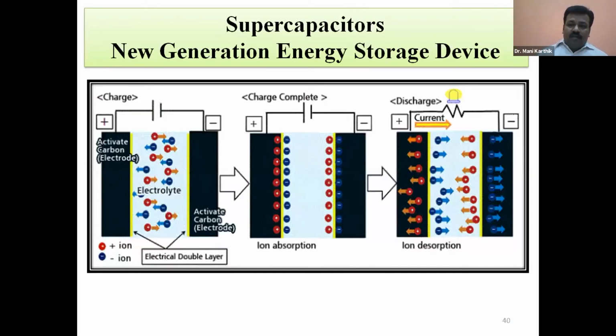So this is the fundamental phenomenon of electrical double layer formation, because porous carbon is coated on the current collectors. If you apply a potential, then because of the polarization, the ions are separated into two different polarities. So we have the formation of the electrical double layer. This is the Helmholtz electrical double layer. Because of this, the charge is stored electrostatically in the activated porous carbon. In the charged state, when you apply the load, the electrical current passes through the load, and we release the discharge state. So this is the method.